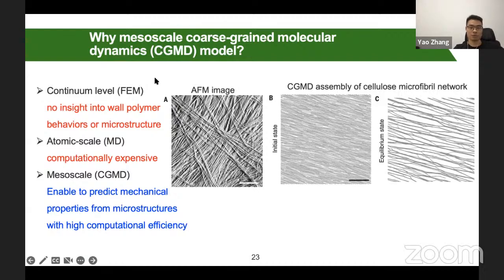There are several choices. One is the continuum level, using FEM. However, in this case, we have no insight into the wall polymer behavior or microstructure. The second one is the MD simulation. However, in this case, it's computationally expensive, because the primary cell wall is not a material which has a very regular lattice structure. So when you use MD simulation, you need a large box to represent the material. So finally, we choose the mesoscale coarse-grained molecular dynamics method.